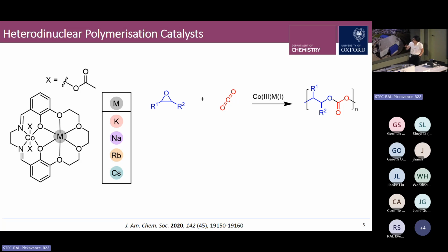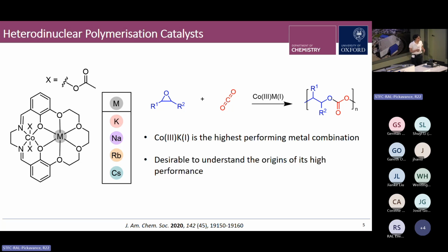And this series of cobalt-group 1 metal catalysts was screened for various different epoxide CO2 copolymerizations, and it was found that the cobalt-potassium combination was the highest performing in each case. But at this point, we were really yet to understand the origins of its high performance, and in particular, whether there are any catalyst structural features that we could relate to high performance, so high activity or high selectivity polymer. And understanding these kinds of structure-activity relationships, as has been discussed in prior talks, is really important if we're going to further understand these catalyst systems and also rationally improve them in future.